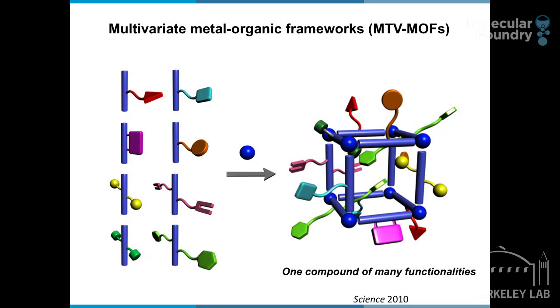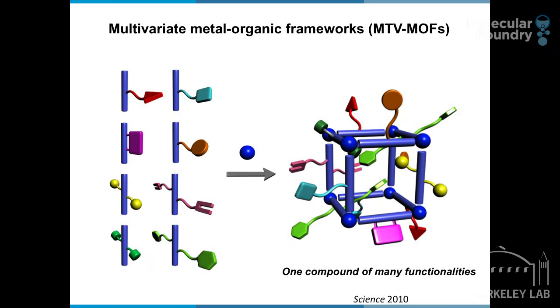So in this final segment, I'd like to share with you just one experiment that has really made a huge difference in terms of carbon capture. In many chemistries, if you try to take multi-component synthesis, or let's say making a material from many different components, usually you get phase separation. With MOFs, you don't. We discovered that the MOF backbone forms regardless of what functionality you have on the link. And so, again, my students have taken these links, the same link but with different functionalities, and assembled them into one structure.